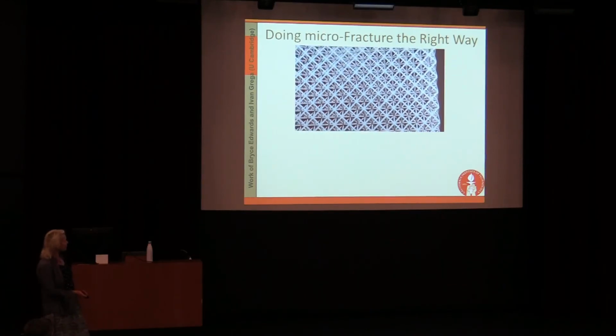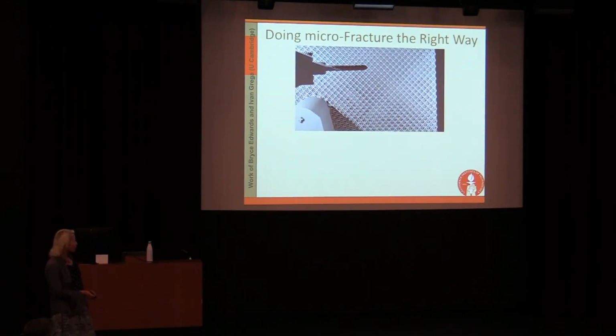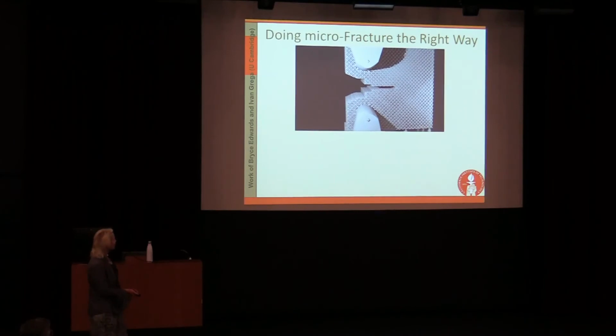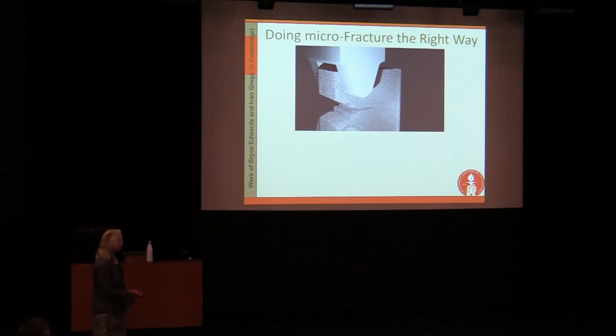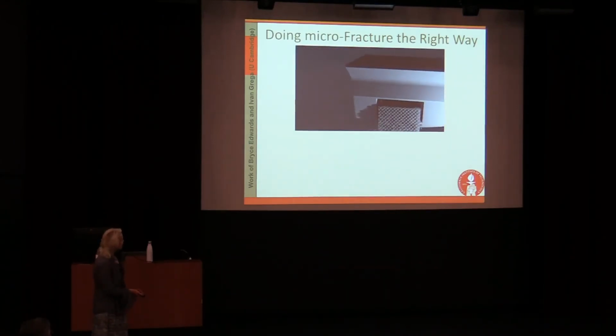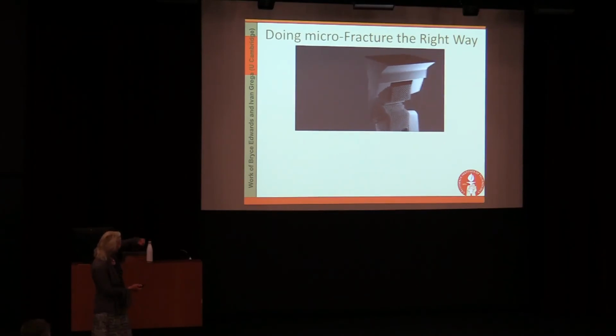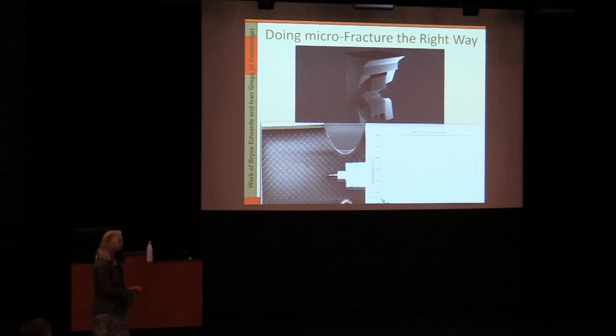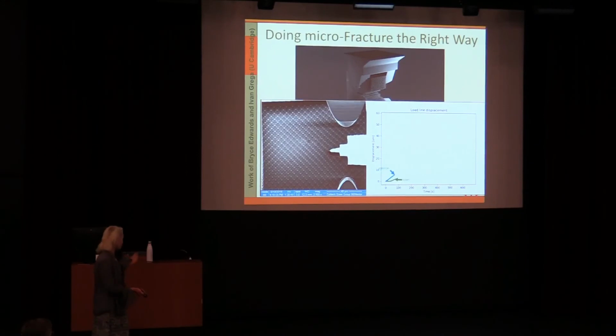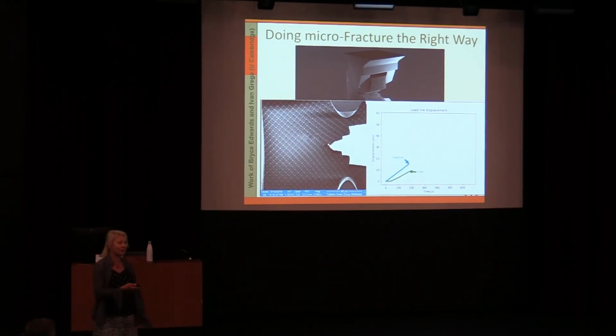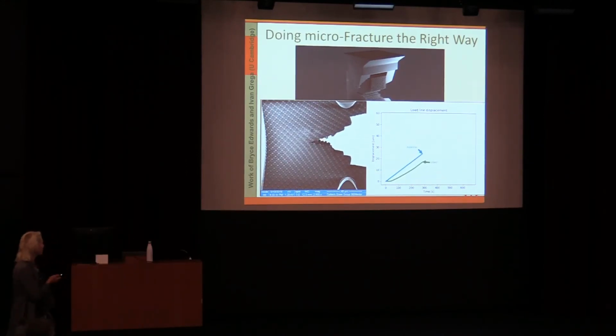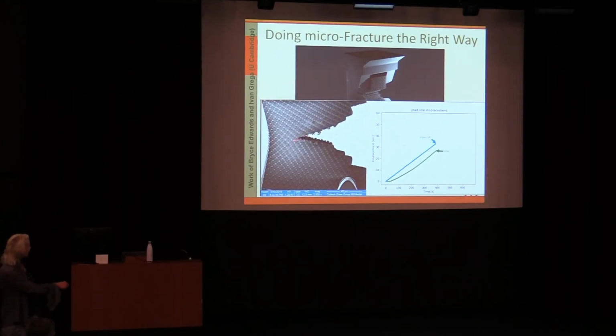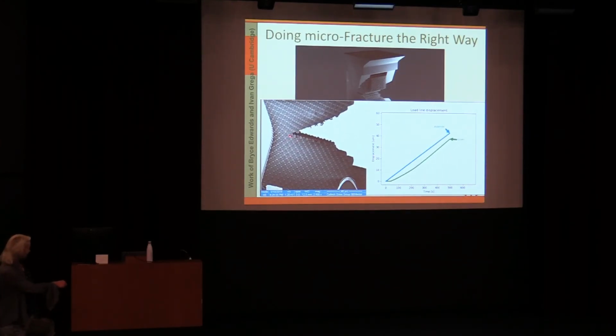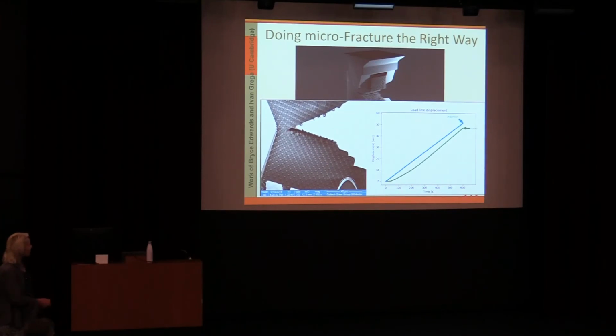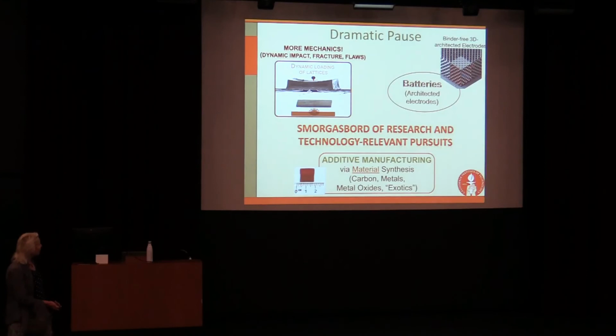So now I have a summer student who figured out how you should really do fracture. The way you do it is you create single edge notched specimens so that you can apply the load homogeneously. And so these are the kinds of geometries that they're testing. And sure enough, of course, they've already made it. This is the thing about Caltech. Their students are kind of brilliant, and so they really figured this out. They're able to track the crack opening, the crack trajectory, and the crack propagation here. And so we're able to track the displacement and quantitate structural toughness of these materials.